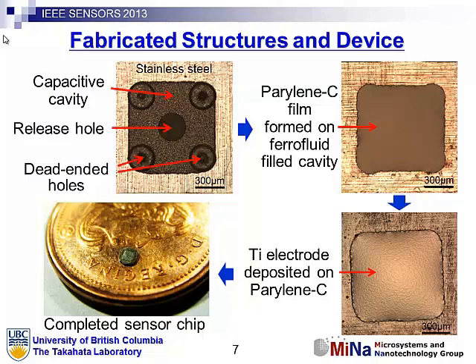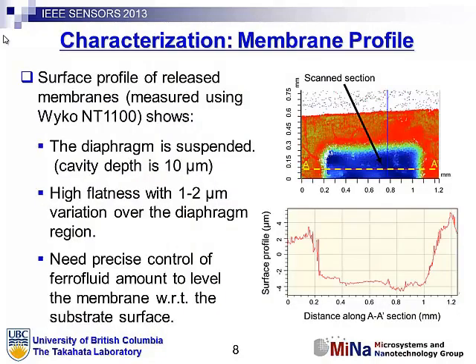And characteristic of all of them was that when the ferrofluid was removed with the permanent magnet, as often occurs in MEMS, where you have a fluid involved, it tends to draw the membrane towards the substrate because of the adhesion between the fluid and the materials itself. So actually what happened in this case is that the cavity was 10 microns deep, but the optical profile of the top surface showed that the membrane was depressed to about 6 microns with relatively good flatness considering the roughness of the substrate. And so what's really going on there is there's a small amount of ferrofluid at the very bottom, which is making up the difference between the 6 microns and the 10 microns.